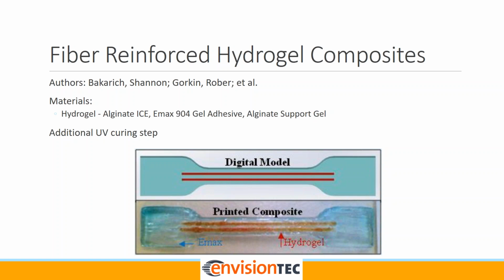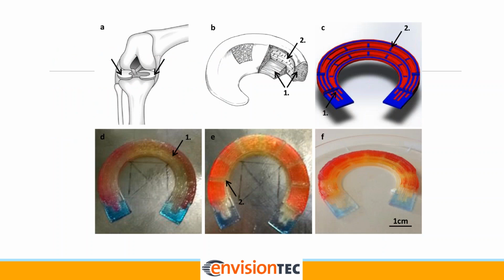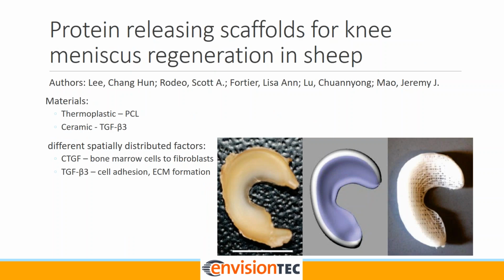Another knee meniscus style study out of Columbia. This one incorporates PCL as a very nice flexible thermoplastic. It incorporates, again, some ceramic to, again, signal bone growth and increase its strength. But then they also go and spatially distribute growth factors. So the white portion has one type of growth factor, and then the blue has a different type of growth factor. And this was to examine if they could induce different kinds of cell differentiation across the cartilage. And they were, in fact, able to do so.